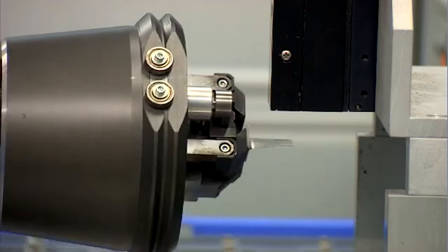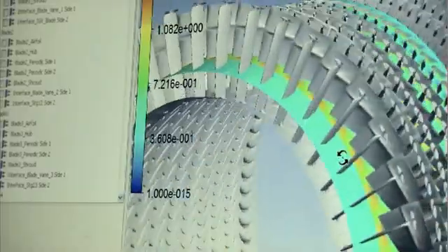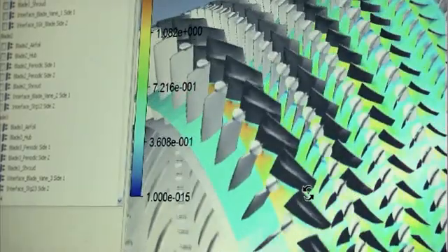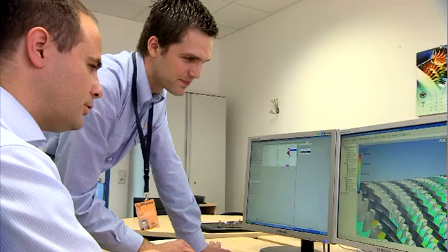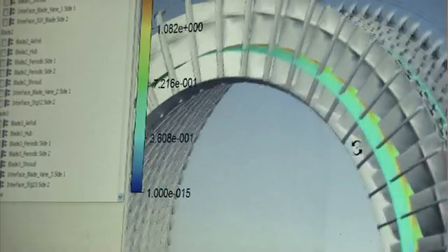During operations, the blade suffered from chord loss due to erosion of the leading and trailing edges. From its first occurrence, erosion has a negative impact on performance. This effect finally leads to the scrapping of the affected blades when the chord length is eroded below the minimum serviceable limit. Scrap values of $50,000 and more per engine are common.